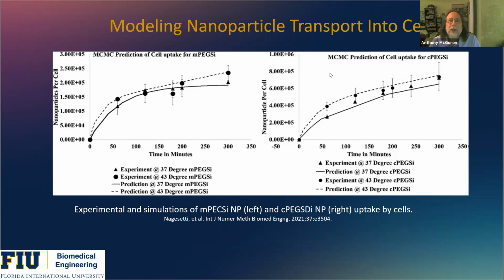And with help from Professor Orlande, we were able to, with my student, develop some mathematical models to predict the uptake. And here I show the experiment in cells, in cell culture, for two different types of mesoporous nanoparticles, a methoxy PEG silane and a carboxy PEG silane. Of course, the PEG is generally considered necessary for evading the opsonization in the blood and making the particles stealth.